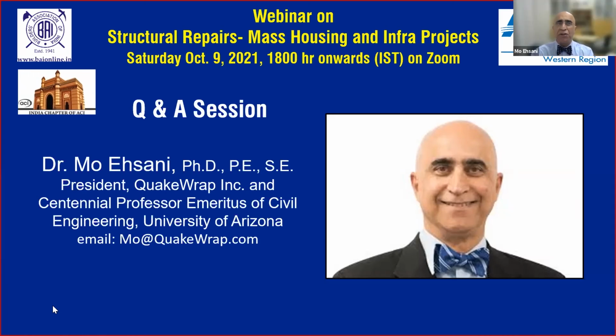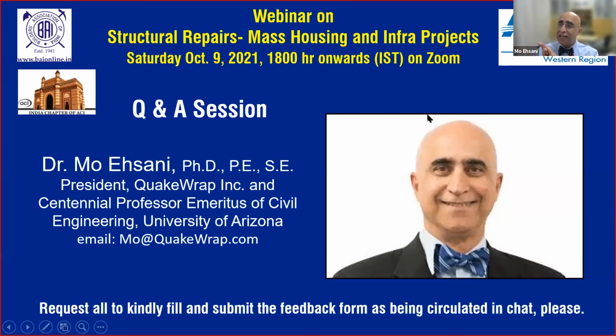No, actually, let me say a few words about fire resistance of these products. What happens with FRP products in general is that if you don't do any special treatment, they are good for all kinds of ambient temperature. We have done a lot of projects in Saudi Arabia, for example, where it gets really hot. That's not an issue. But when the temperature reaches about 80 degrees centigrade, which is not much, the resin starts to become soft. Not the fibers. The fibers can take very high temperature, but the resin becomes soft.